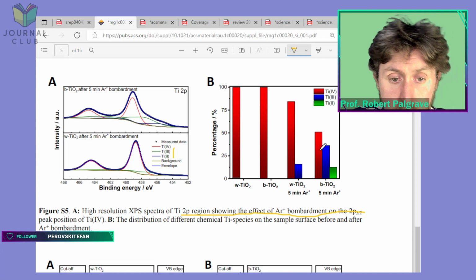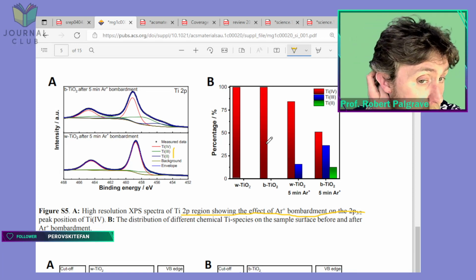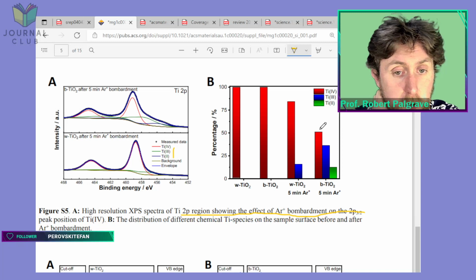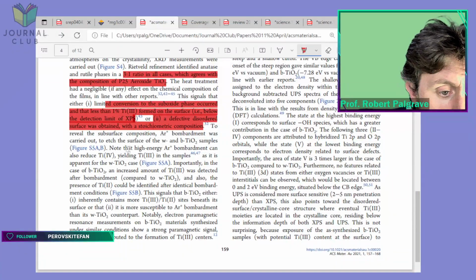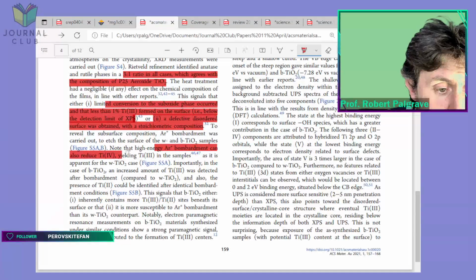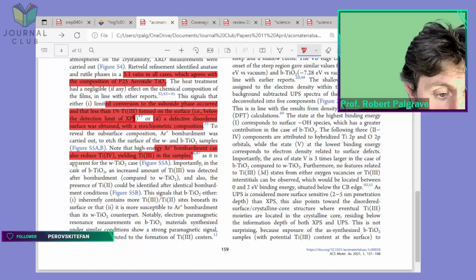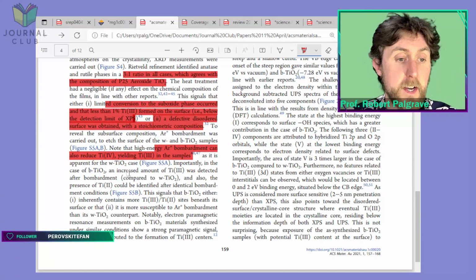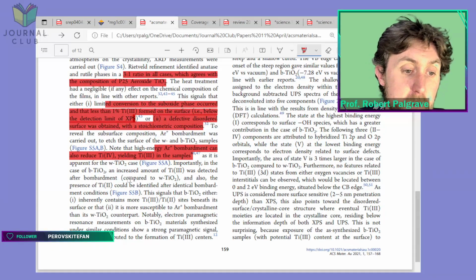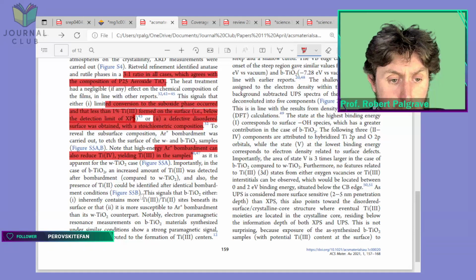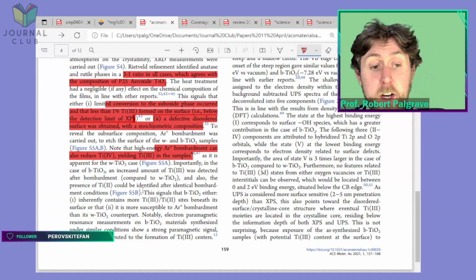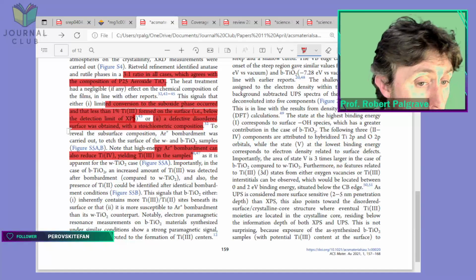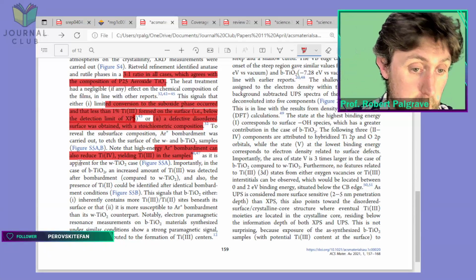They're showing graphically the amounts of each of the different oxidation states of titanium, before argon sputtering and after sputtering. Note that high energy argon bombardment can also reduce titanium 4+. Yeah, that's what I just told you guys. Importantly, in the case of black TiO2, an increased amount of titanium 3+ was detected after bombardment compared to white TiO2, under identical bombardment conditions. So they're doing more reduction. Black TiO2 is easier to reduce with argon ion bombardment compared to white TiO2.